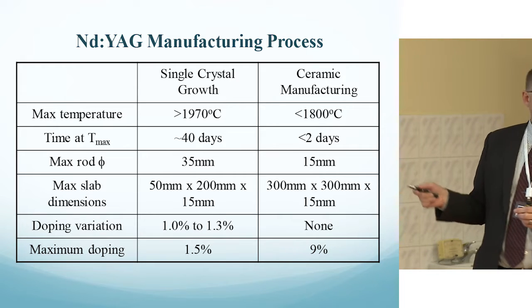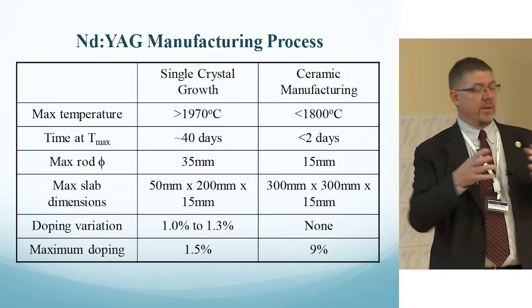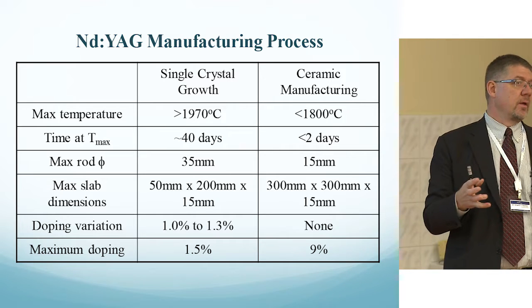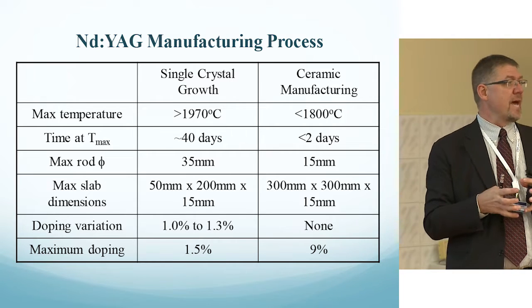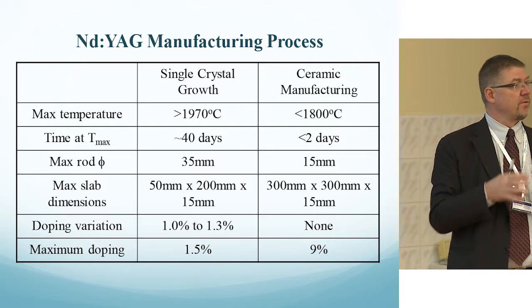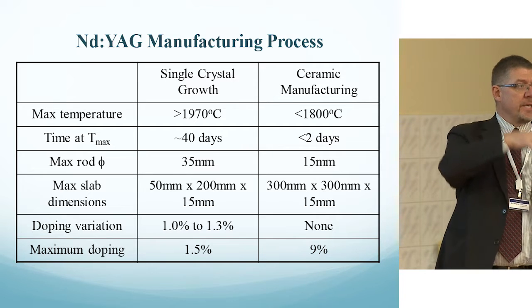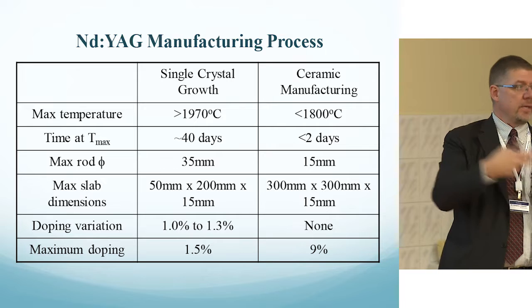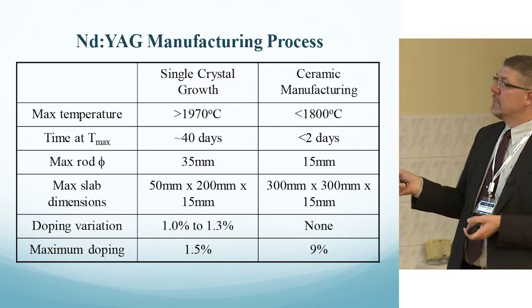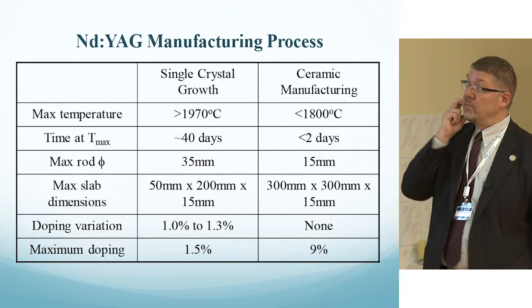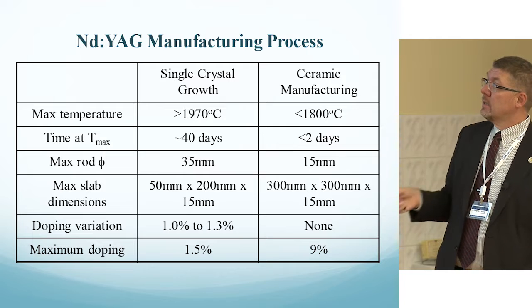Maximum rod diameter is smaller because as you sinter these ceramics, it's all based upon diffusion of the heat out of the material during the sintering process. And there's only so much that you can do and keep it single phase and let the heat be uniform through the material. So last I saw, it was right about 15 millimeters with good clean aperture.